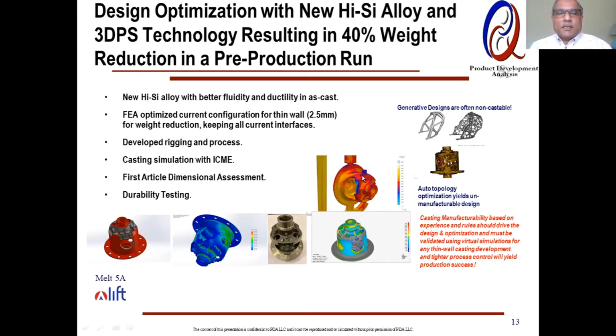So you can see here, extensive process simulation, where we were able to predict the microstructure, mechanical properties, and wanted to make sure it has the desired soundness. One of the issues you get into when you try to make 2.5 millimeter wall iron castings, you have to be concerned with the carbides or the white cast iron formation, which is going to impact your ductility and the fatigue performance. So I think we came up with a pretty good solution and got good results.